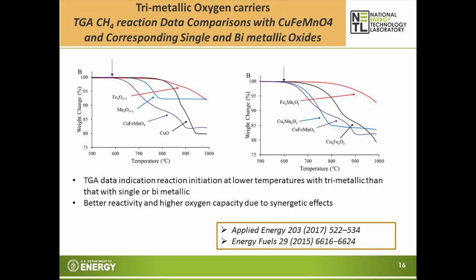Recently we have been also looking at trimetallic oxygen carriers. We looked at a copper, iron, manganese oxygen carrier, and these are some of the TGA DSC data during temperature ramps. You can see the weight change as a function of temperature. Again, for comparison, I also included the single metal oxide data. As you can see, when methane was introduced to the copper, iron, manganese, and we conducted the temperature ramp, the reaction starts at a lower temperature with the trimetallic as compared to the corresponding single metal oxides.